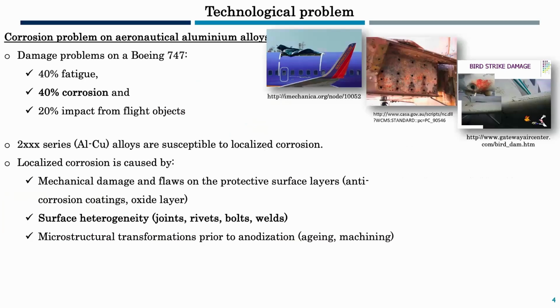Okay. The main technological problem that is met in several damage problems is corrosion, with a percent of approximately 40% regarding an investigation in Boeing 747. The 2000 series aluminum copper alloys are highly susceptible to localized corrosion, and one of the main reasons where localized corrosion is caused is the surface heterogeneity, such as the joints and rivets.